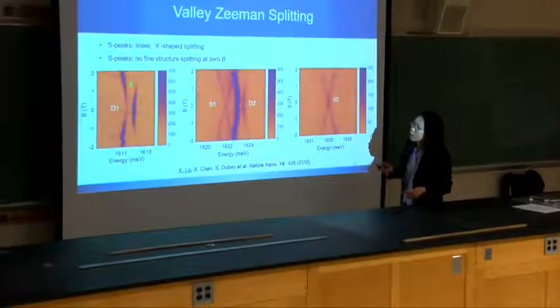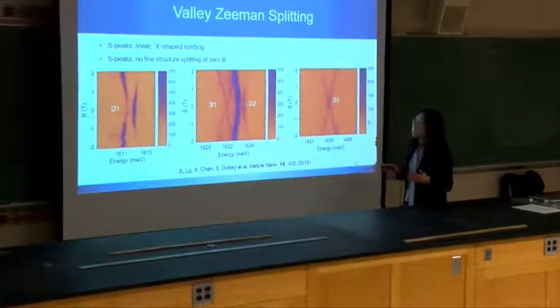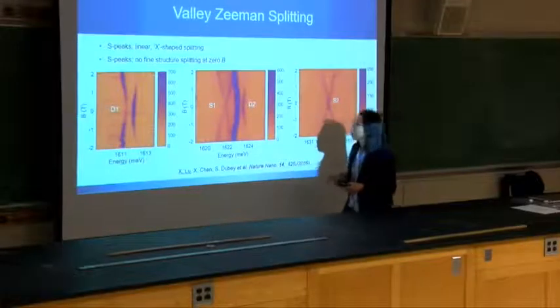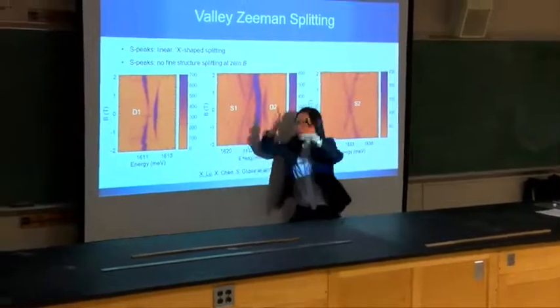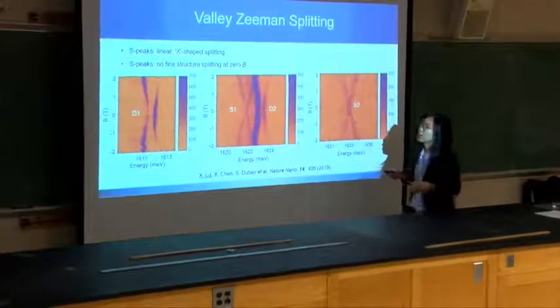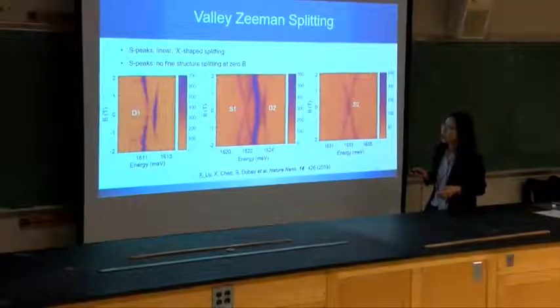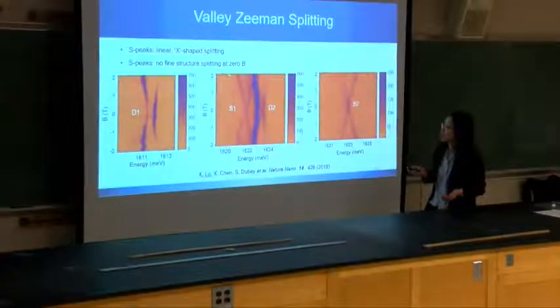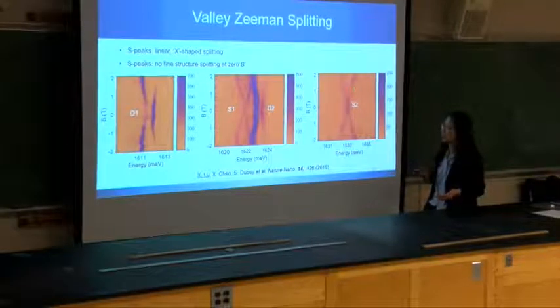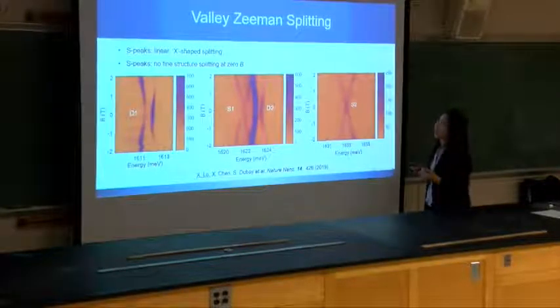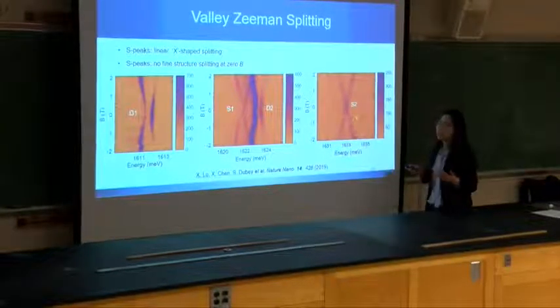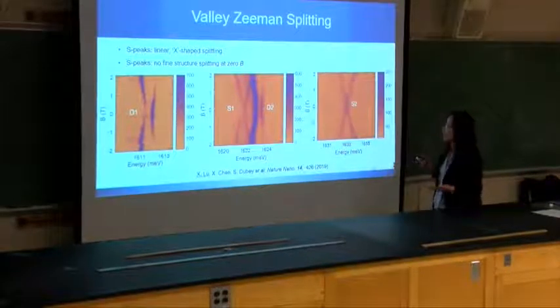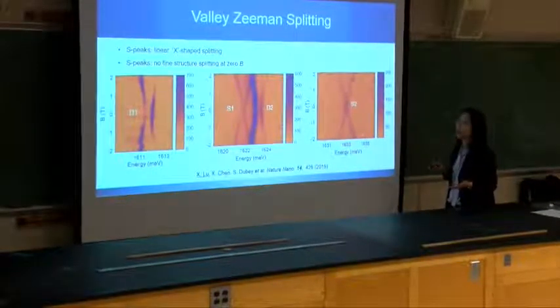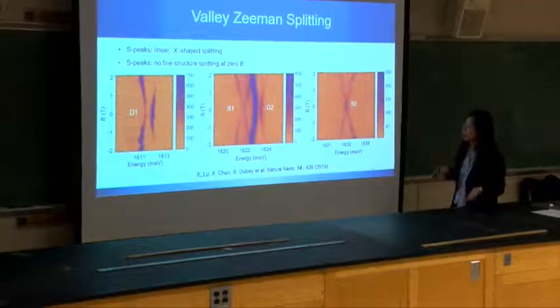So here we see the valley Zeeman splitting. The D1 and D2 neutral peaks have a zero-field splitting, so it will be a parabolic dispersion. And the S peak, as it has no fine structure splitting, shows a linear X-shaped dispersion. This further confirms that there's no exchange, or at least the exchange is very small, smaller than the resolution of our detection, which is around 50 micro electron volts.